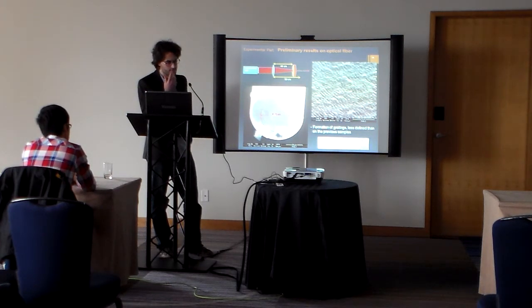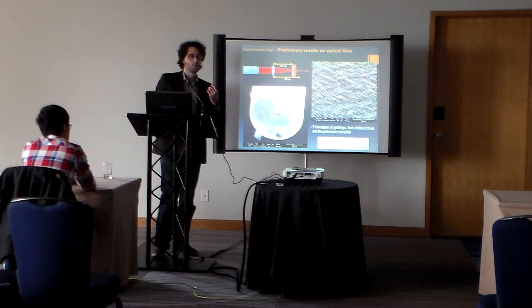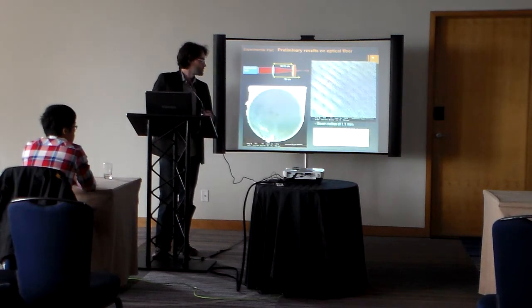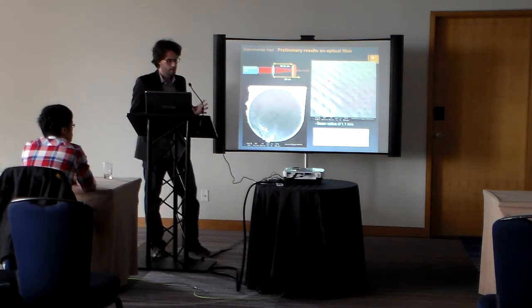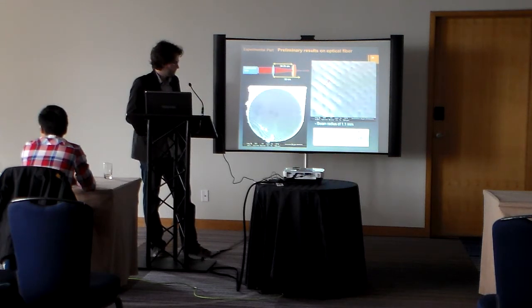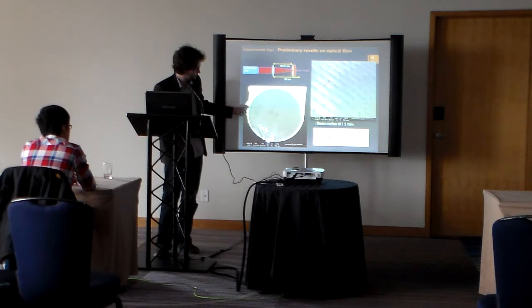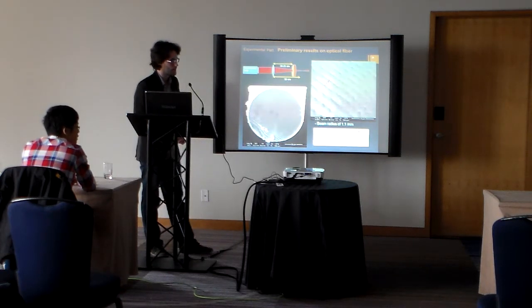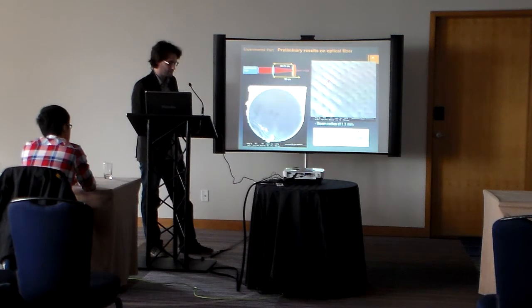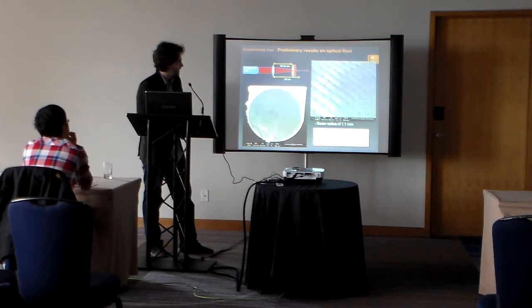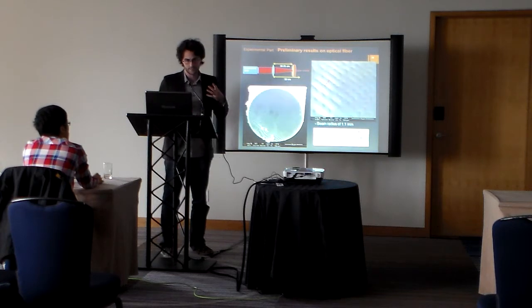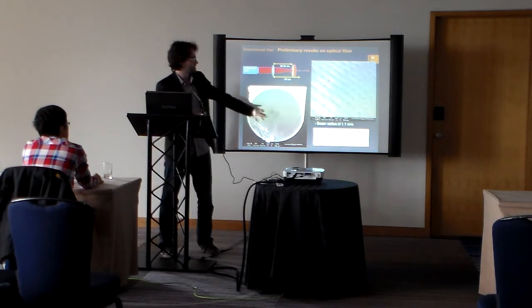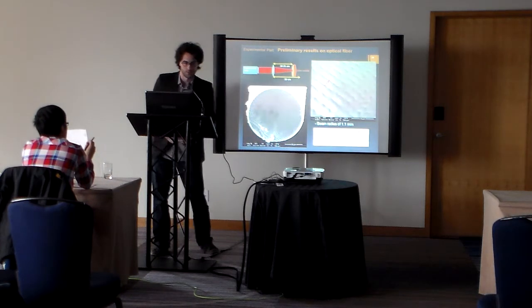So we tried a different approach: we just put the fiber a bit closer to the lens. We thought that the energy dispersion would be more uniformly distributed. But as you can see, we obtained quite a strange structure on our fiber. We don't yet know what happened. We obtained the same kind of structure on other tests, but it is clearly not the same kind of grating that we obtained before. It is really wider, with a period of 3.25 microns.